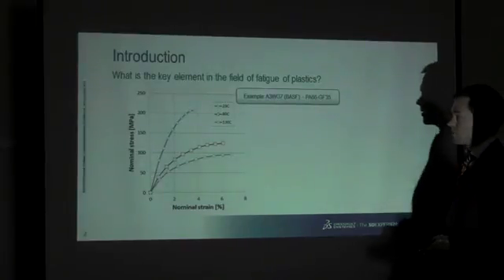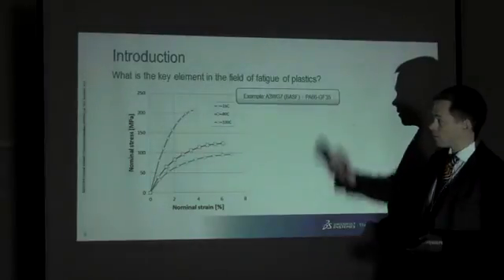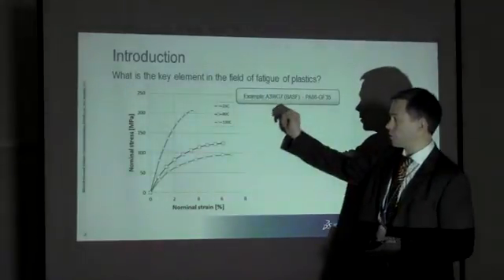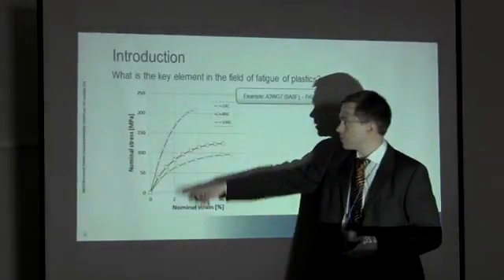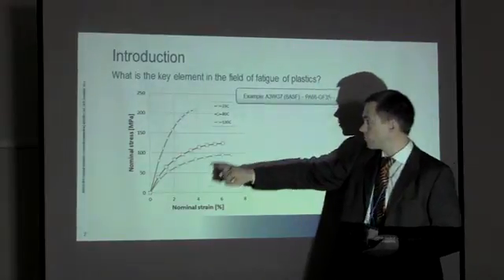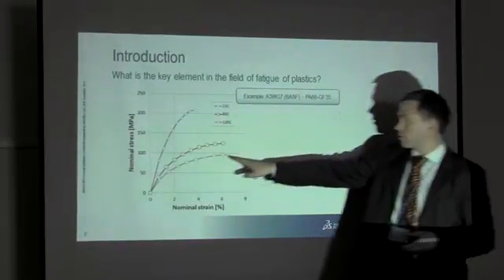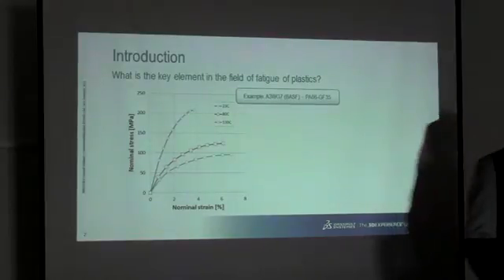If we look at this here, this is a very typical example. Glass fiber reinforced nylon 66. Very simplistic. This is a monotonic stress strain curve on the left-hand side of the picture. The blue line represents 23 degrees C, red line 80 degrees C, and the green line 130 degrees C. Easy enough to understand. Yes, you can clearly see the temperature dependency of the material, and this even being a reinforced material. But what's the point?